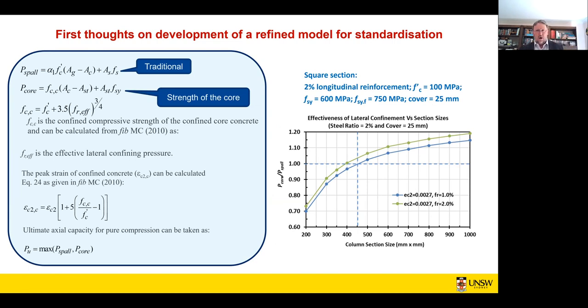The way we do design is this traditional way here, or the way we deal with columns is we put this alpha factor here, and that is the point of when the cover spalls away from the column, and we basically lose the section. Let's take the core and let's think about what's happening to that. And if I confine the core sufficiently, I know two things. I'll increase its strength, but more importantly, I will increase its strain at peak strength. Now, it might increase the strength only by a few percent, but it increases strain considerably. Now, I'm not going to go into these models. That's not so important. But let's say that we developed a model for the core and a model for our traditional column, and we simply looked at the maximum of those two conditions.